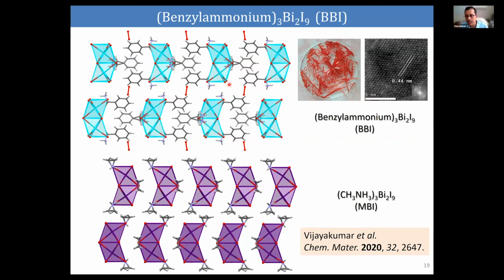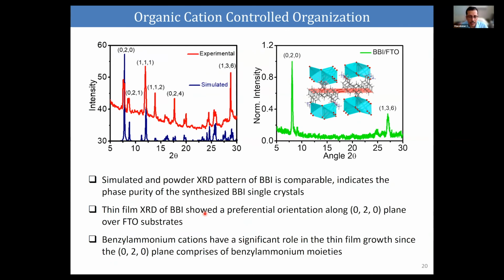The top one is our material, which is giving very nice crystals and with a nice scattering. And the lower one is the standard material. We made that material for comparison. And the interesting thing is that this material actually shows a preferential orientation along the 0-20 plane, which is actually controlled by the packing of the organic cation. So normally in most of the perovskites, the packing of the material in the film state is controlled by the inorganic octahedron. But in our material, this organic plays a key role, acting as a template and controlling the film formation direction.